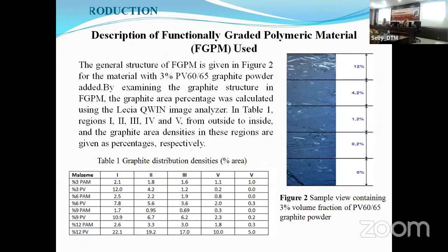So we add graphite to the epoxy resin, and we use an image processing program to detect how much graphite is inside, the graphite size, what the situation is at the outer surface, and what the situation is in the transition gap. We can use the image processing program to get some distribution data. Look at that, it's some distribution data.